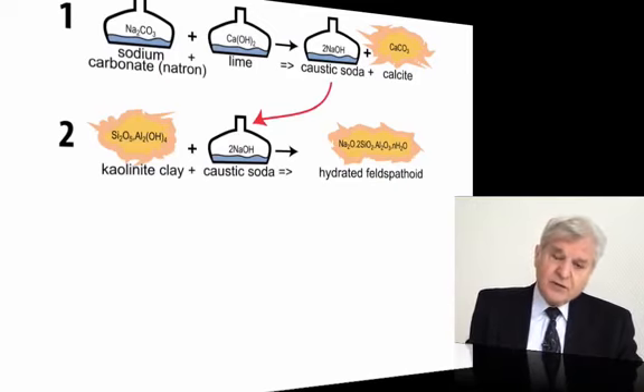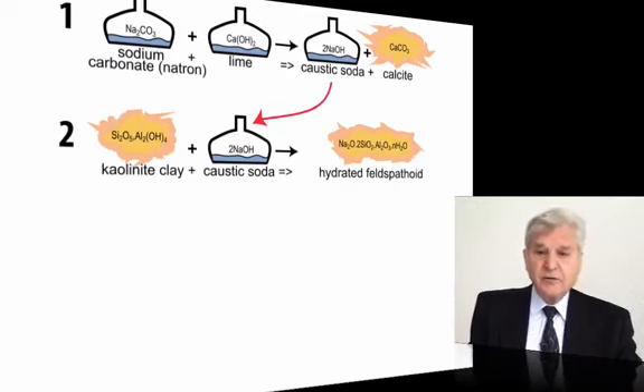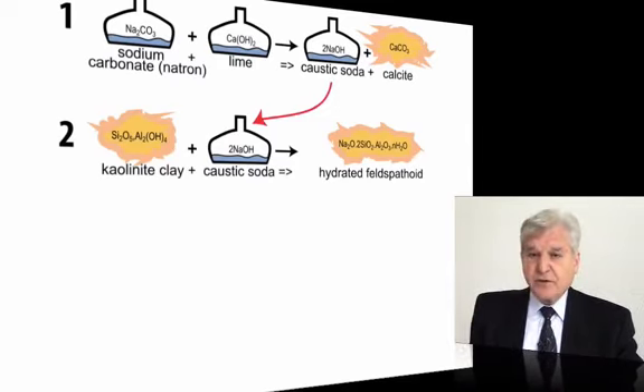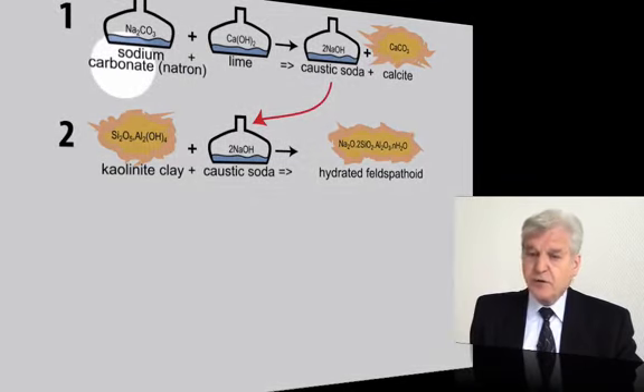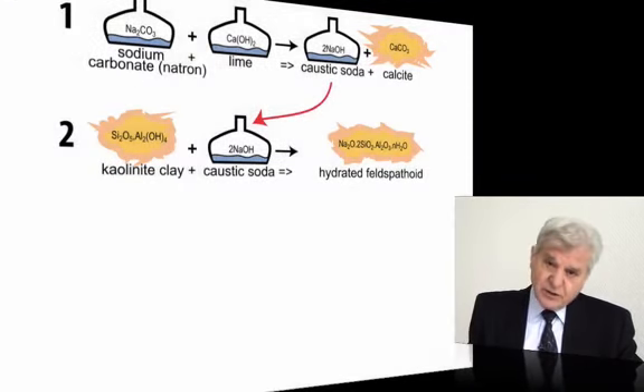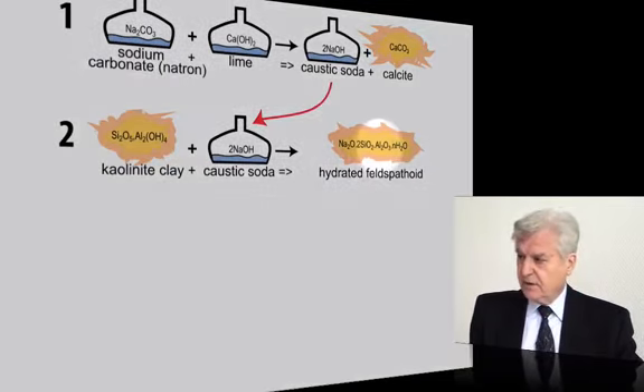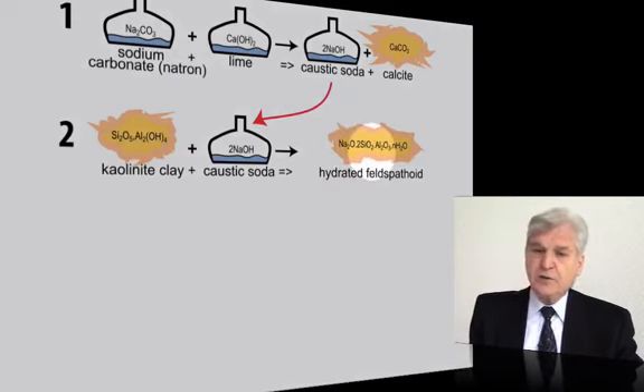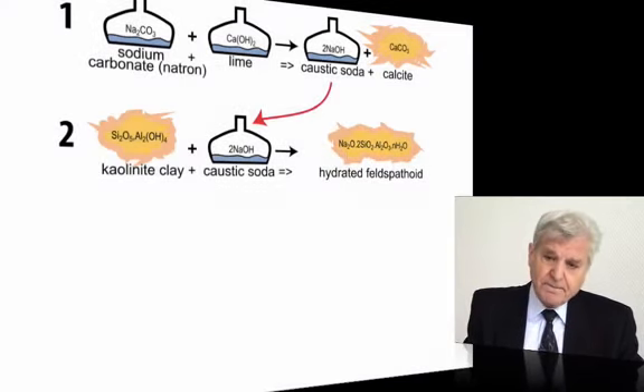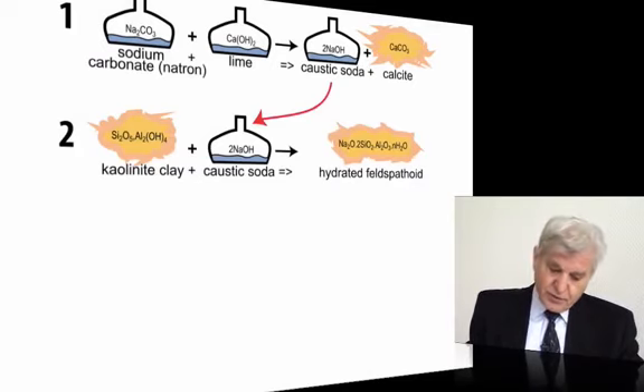Until I got the first results of the electron microscopical analysis from my friends Barzoum and Hug. The first result was that they did not find remains of natron, sodium carbonate. If the chemistry was right, we must have remains of sodium carbonate. They did not find it. Second, they did not find the sodium aluminum silicate that I was claiming. And this was a little disturbing.